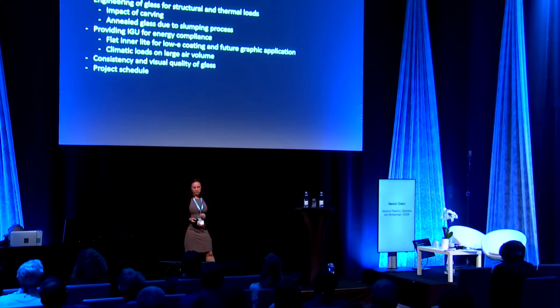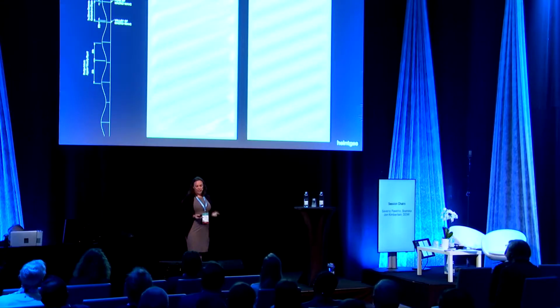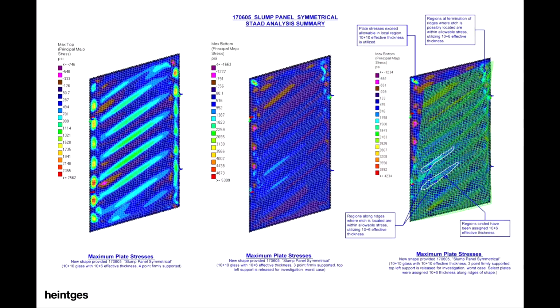So we got started. The engineering analysis started with geometry from the design team. See here. Heintges used that 3D geometry for preliminary engineering of the slumped glass, checking for stress and deflection to confirm the viability of the architectural design. We looked at different reductions in thickness, different assumptions for the areas where the glass was to be carved.